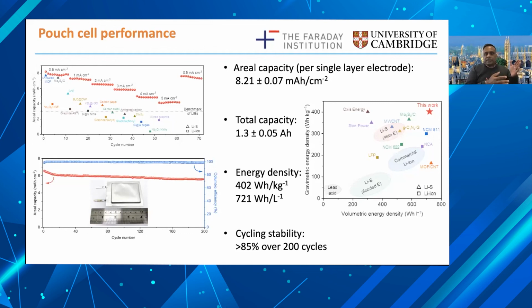Here the cathode is our 1T phase MoS2 that's been loaded with sulfur. We use the standard electrolyte, and the anode is lithium. When we test these pouch cells, we again obtain extraordinary properties. We have very high areal capacity, and our devices show a total capacity at the amp hour scale. This is quite rare in an academic laboratory, to make devices with amp hour capacity and energy density values of 402 and volumetric density of 721. These are among the best performing pouch cells made in the Faraday Institution consortium.